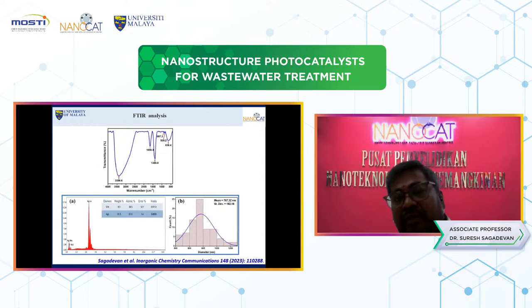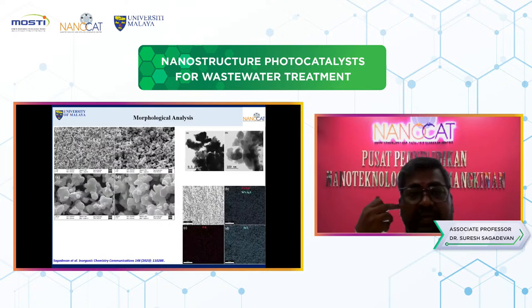And then again, we confirmed the silver and oxygen stretching vibration, which is confirmed from the lower wave number of 638, and as well as we confirmed with the EDX analysis, the silver and oxygen. This is a material confirmation for the silver oxide. And as well as you can look at here, the morphology of the silver oxide, the A and B and C and D are different magnifications.